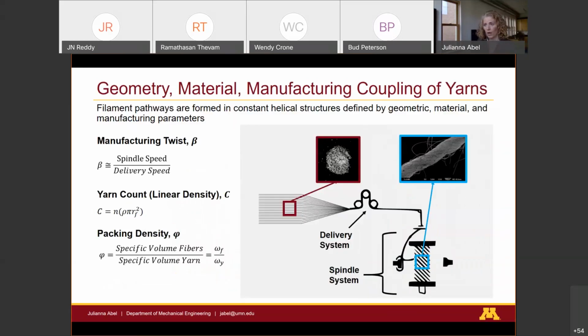And we really want to understand this coupling between the material that we're using, the geometry of the yarn, and the manufacturing parameters. It's a really well-established relationship that our manufacturing twist, our density, and our packing density all rely on these manufacturing parameters that we see in our system. So we're using a traditional ring spinning technique to create these, where we have a bunch of parallel fibers that come into our system. They're all twisted together, and depending on our delivery speed and our spindle speed, we get different amounts of twist.